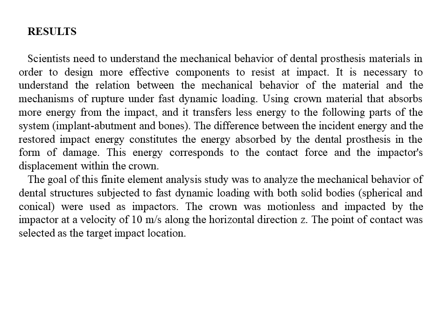Scientists need to understand the mechanical behavior of dental prosthesis material in order to design more effective components to resist impact. Using crown material that absorbs more energy from the impact transfers less energy to the following parts of the system: implant, abutment, and bones.